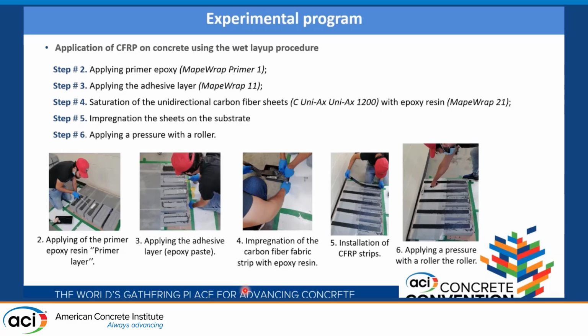So the second step is applying the primer epoxy resin. After that, applying the adhesive layer, which is epoxy paste. Fourth step, the impregnation of the carbon fiber fabric strip with epoxy resin. Fifth step, the installation of the CFRP strip. And finally, applying pressure with a roller in order to eliminate any voids.